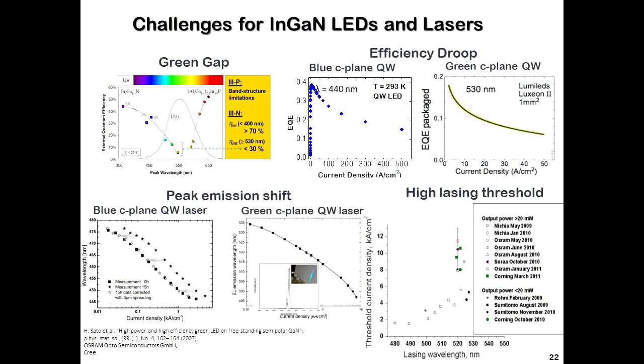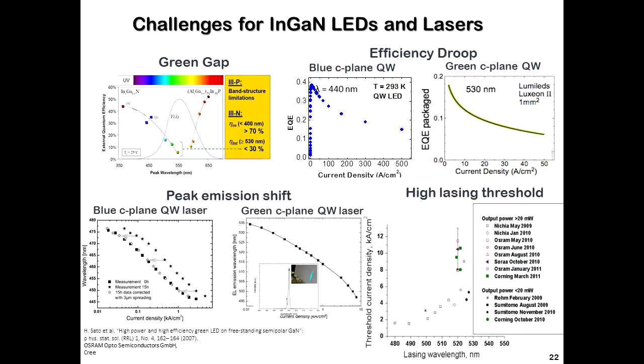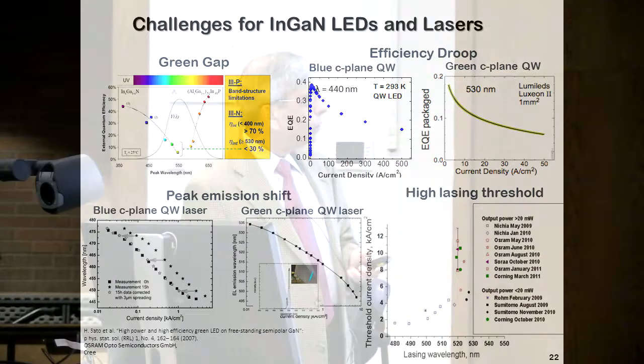Then you have this shift. I had mentioned this blue shift. You have this shift as you apply bias, which you have to in a real device. The output wavelength shifts. So let's say you've designed a blue device. By the time you are operating it, it's emitting some other color. And you don't want that. Same thing for the green. And then in lasers, because of this lack of overlap and so on, the threshold currents are enormously high, 10 kiloamps per centimeter square. So these are some of the current problems.